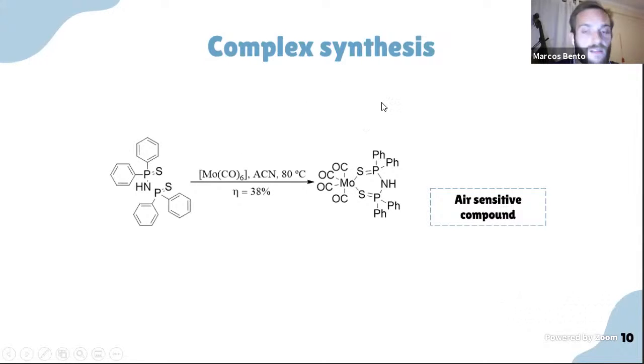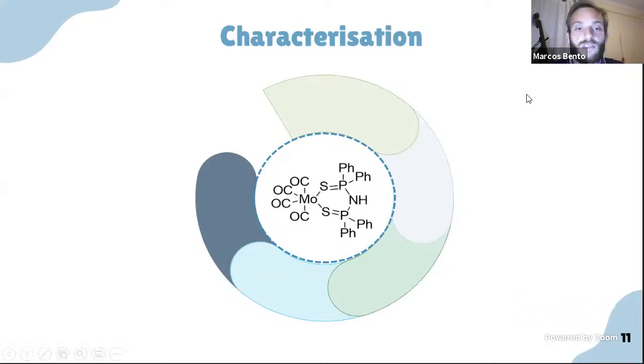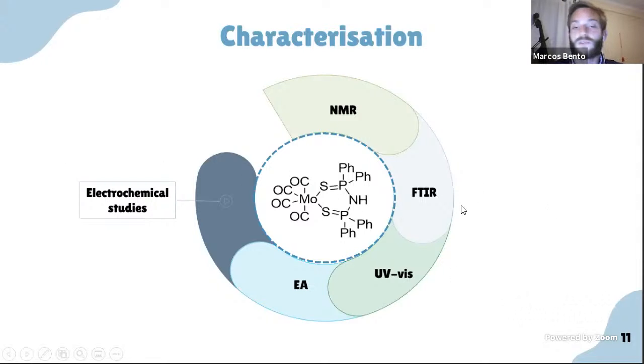To do the complex synthesis, we react the ligand with molybdenum hexacarbonyl under inert atmosphere, building an air-sensitive compound that will be tested for CO2 conversion. So we characterize the ligand through NMR techniques, FTIR, UV, elemental analysis, and finally, after confirming the purity of the compound, we did some electrochemical studies in order to understand if this compound can be a good catalyst for this type of conversion.